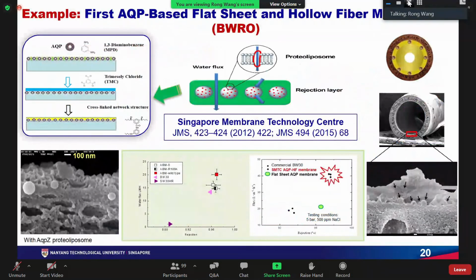Actually, this method was invented by us at the Singapore Membrane Technology Center. We reported the first aquaporin-based flat sheet membranes and aquaporin-based hollow fiber membranes for brackish water and water reuse application in 2012 and 2015, respectively. For flat sheet membranes, the water permeability can improve by 50%. For hollow fibers, the permeability increased by 100%, double the permeability, while maintaining similar level or even higher salt rejection.